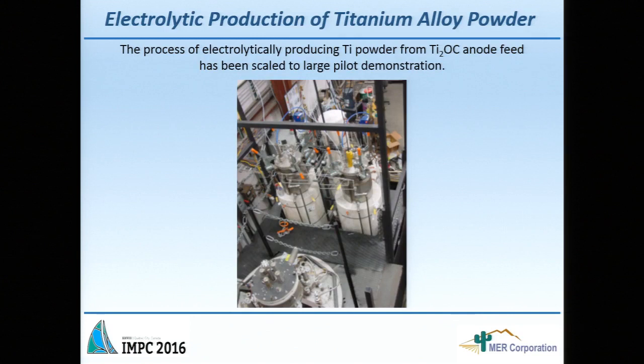And based on this idea, we got funded, and we actually scaled it up to a 50 pound per day electrolysis process. So we had a carbothermic step to produce the Ti2OC. We had electrolysis, and the electrolysis cell has a lot of innovative design, with high temperature pumps, to be able to push the electrolyte to collect the titanium and recycle it and harvest the titanium powder, take the titanium powder into the next step, evaporate the salt, and recycle it into the cell.